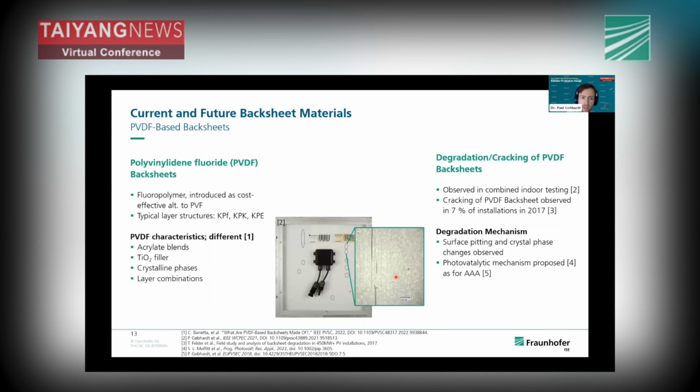All right, I want to comment on PVDF simply because it has been an extremely relevant product on the market in the last years. So of course, we all know it's a fluoropolymer. It was introduced as a cost-effective alternative to PVF, the conventional Tedlar material, and products on the market or backsheets that we see in our lab consist of different structures.